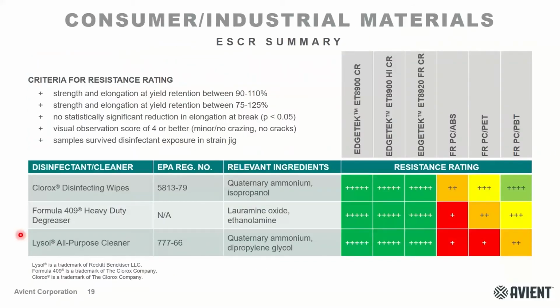So here's another example. Now this is looking at our Edgetek materials. We have our base grade, the high impact grade, as well as our FR grade. And in this space, we tested against a variety of different disinfectants or cleaners, such as Clorox, Formula 409, and Lysol. One thing to note is that Formula 409 is not technically a disinfectant, since there are no active ingredients. But at the time that we were doing this testing, it was sometimes difficult to find the disinfectants. But there are other relevant ingredients that do pose problems, which you can see here with the PCABS, PET, and PBT, that the Formula 409 definitely poses some challenges, as well as the Lysol All-Purpose Cleaner. So once again, though, our Edgetek materials, the T8900 series, perform very well in our visual observation and our tensile retention data.